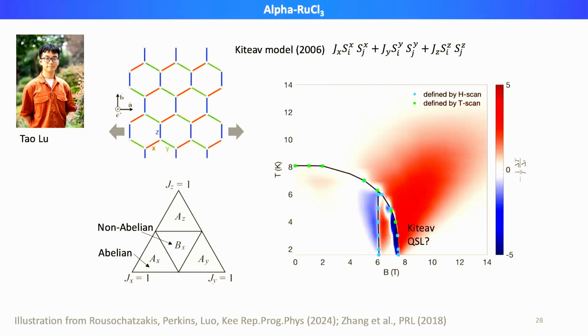So one example of what we wanted to use strain to study, right? This is some of our recent results using strain as a thermodynamic probe to study frustrated systems. So in this particular experiment, we are studying alpha ruthenium trichloride, which is the prime candidate material realization for Kitaev's bond-frustrated spin model. So in our experiment, we apply a small AC strain to the material and measure the temperature change that's induced by the strain.